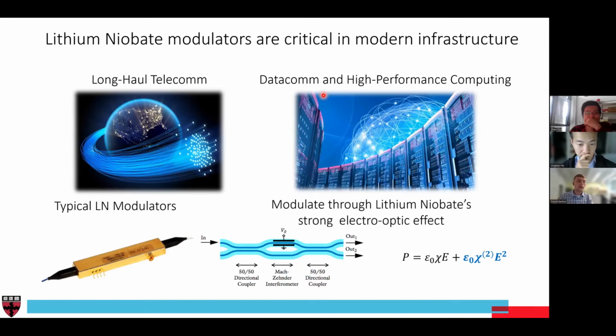And it is because it is one of the best electro-optic materials that we can grow in very large volumes. That allows us to make actual bulk modulators. So on the bottom left is a picture of one of these devices where we have optical fibers coming in, we have a bulk crystal, and we have light coming out. And what we're able to do is make these optical waveguides inside of lithium niobate by diffusing titanium into the structure. And by applying an electric field in one section, we can convert electrical ones and zeros effectively into optical ones and zeros by changing the actual output response. And this is done entirely because of this electro-optic Chi2 parameter that only exists in non-centrosymmetric materials.